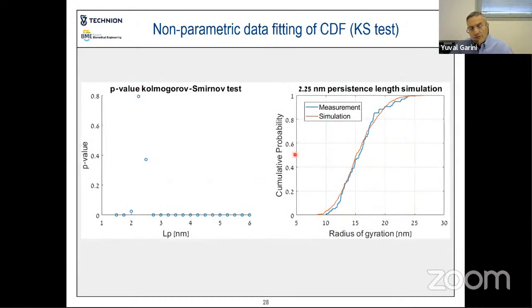And in order to fit the simulation to the measurement, we adopted the non-parametric data fitting of the cumulative distribution function based on the Kolmogorov-Smirnov test. And you can see here in red the CDF of the simulation, and in blue the CDF of the measurement. It's actually an excellent method for doing such a non-parametric fit. And then we tested the fit with different persistence lengths that was used for the simulation, and we picked the persistence length that gives the best quality of the fit.